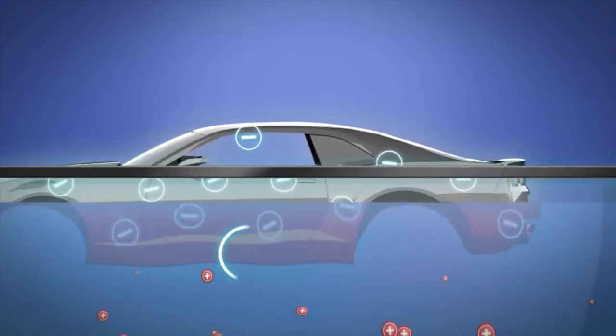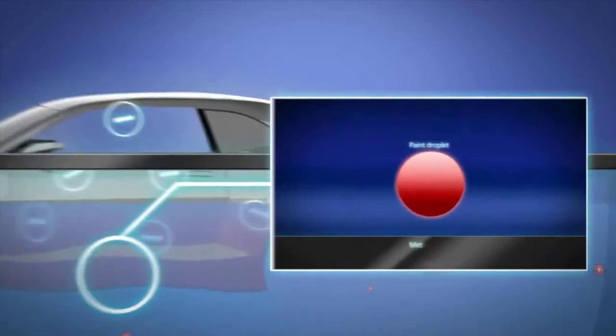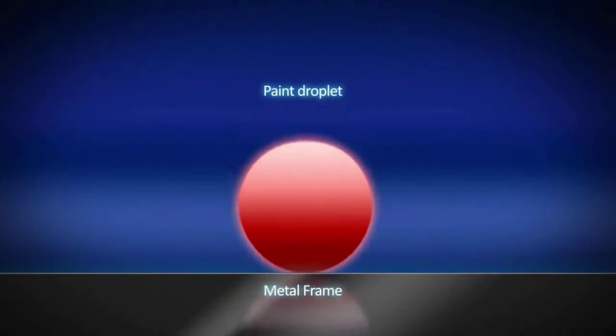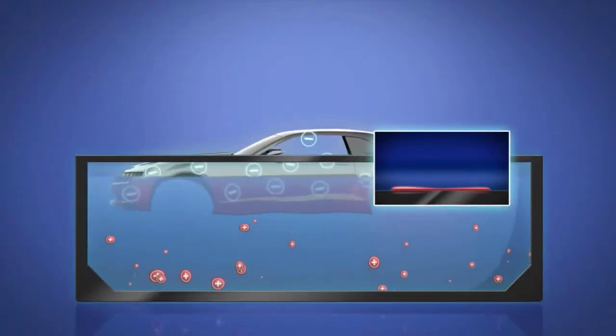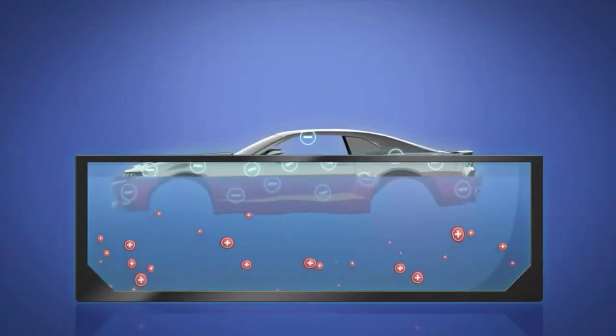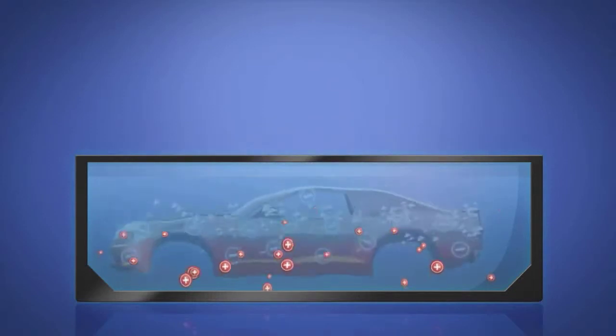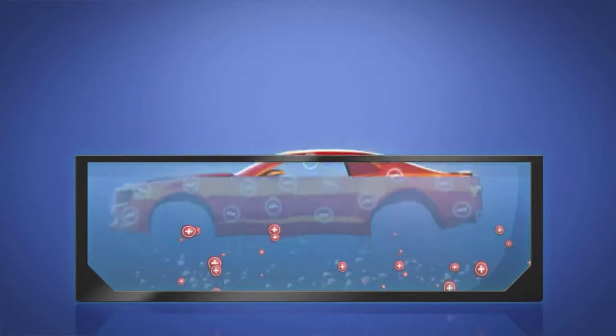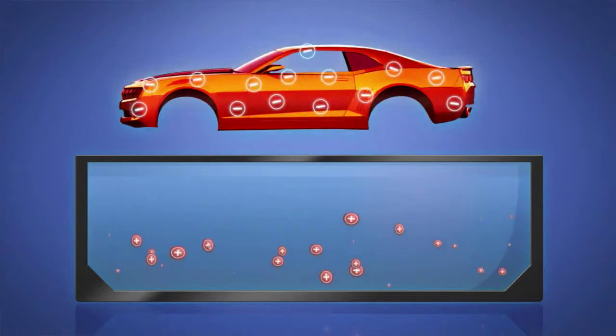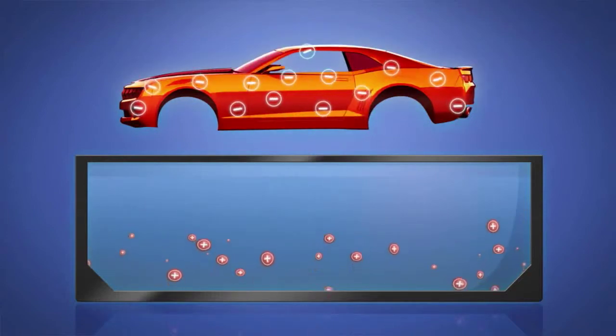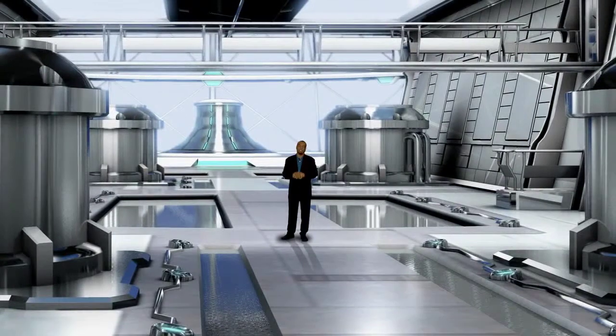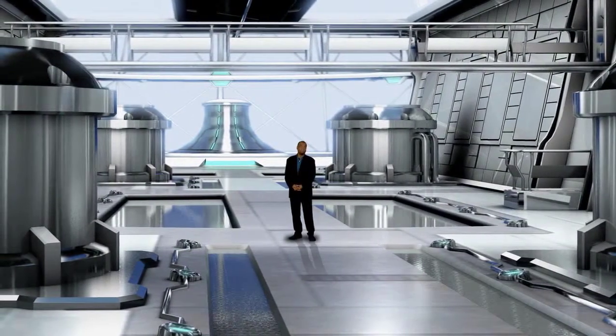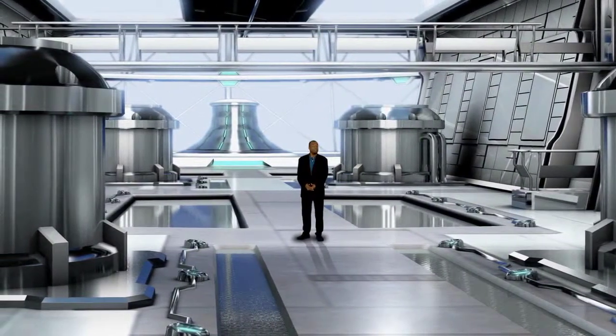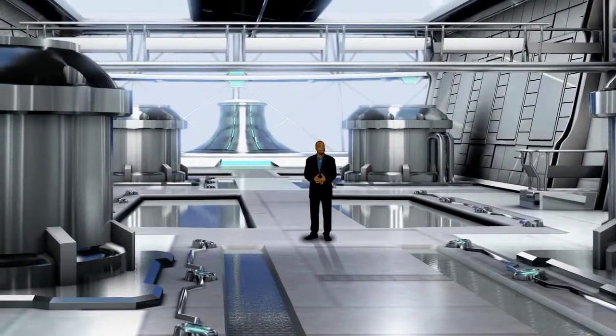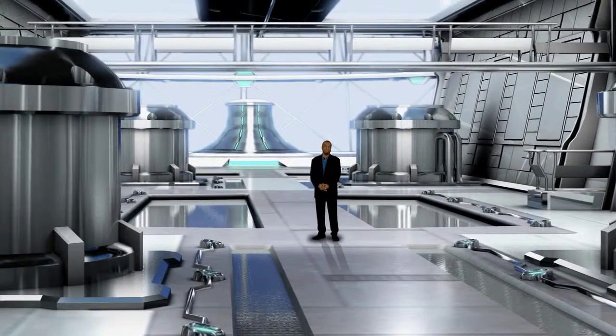The material that needs to be protected is submerged into a water-based coating. In this water-based coating, the polymer, pigment, and additives are dispersed but stable until it is attracted to the metal electrode. An electrical chemical reaction occurs to neutralize the coating, depositing it evenly on the metal substrate. As we all know, corrosion begins with a defect, either in the coating or the substrate, but by being able to control film thickness, the polymer deposits on the metal until nearly defect-free.